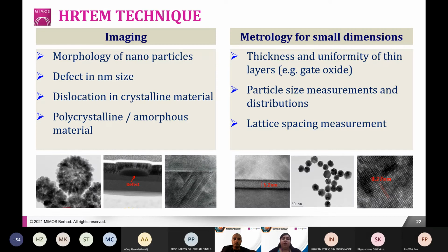All right. So the information the technique gives is the morphology of nanoparticles, and the defects in nano size, so we can see them further. Sometimes in FIB SEM, we can't really magnify further. Maybe I'll show you the example later. So you can't see the defect clearly, but in TEM, you can identify and see the defect clearly. And then we can also identify whether the sample is polycrystalline or amorphous material by doing the SAED technique.